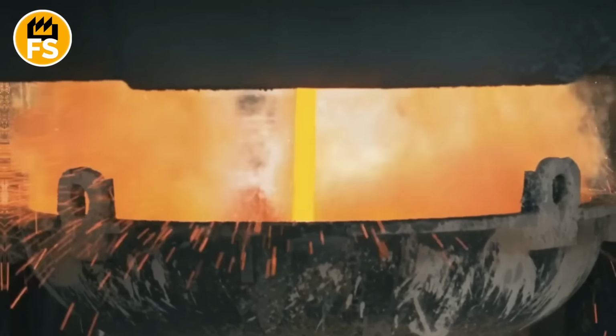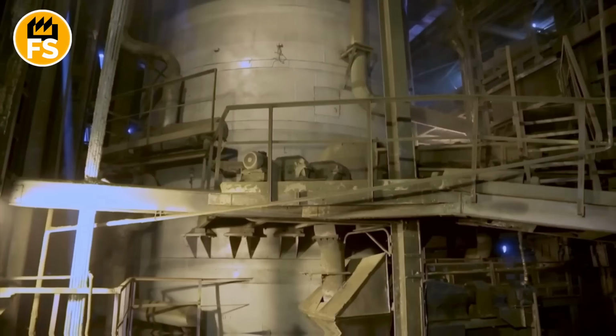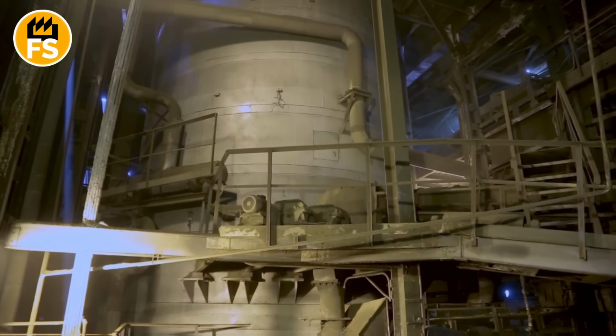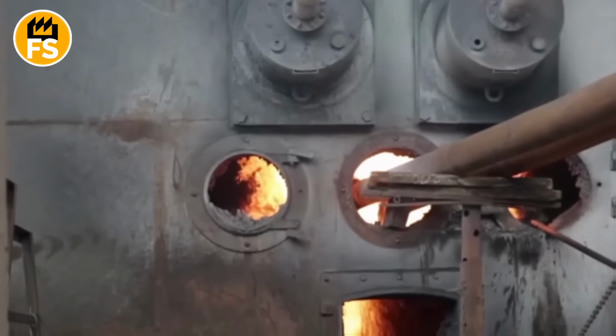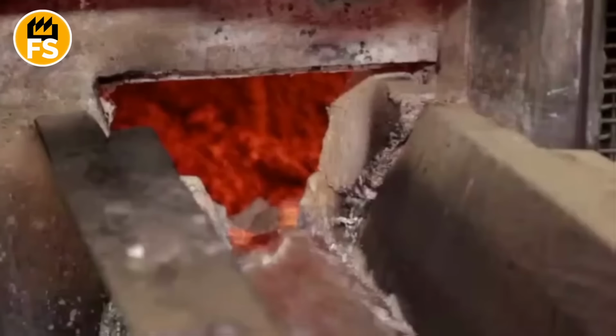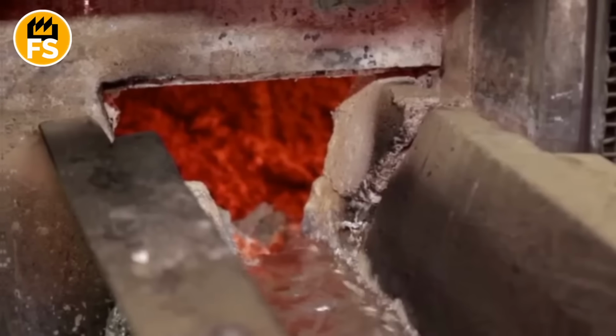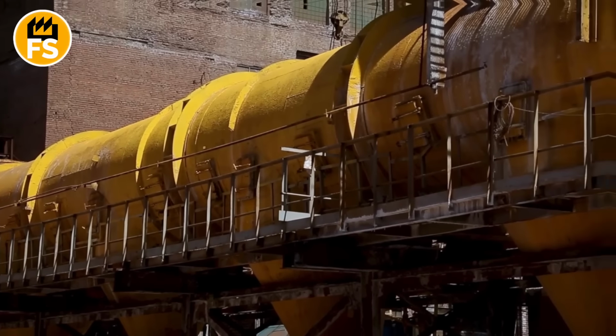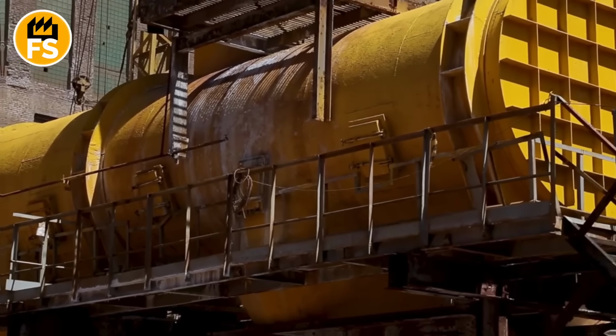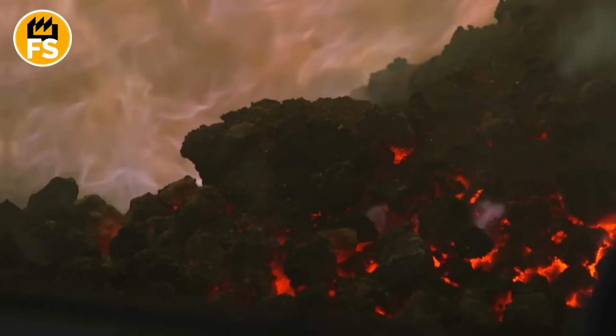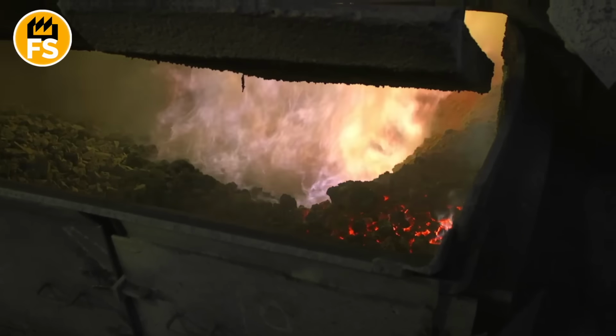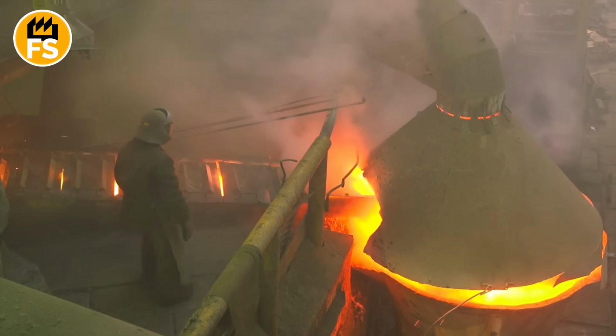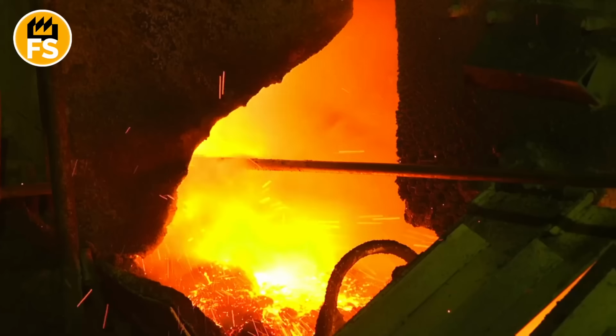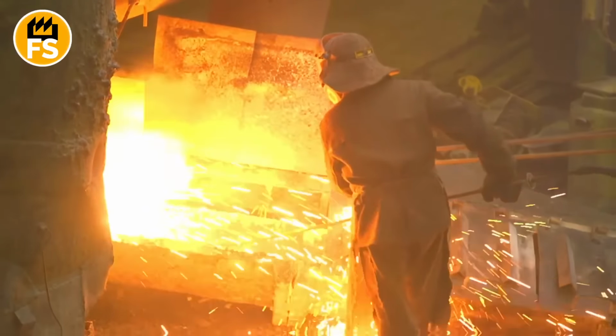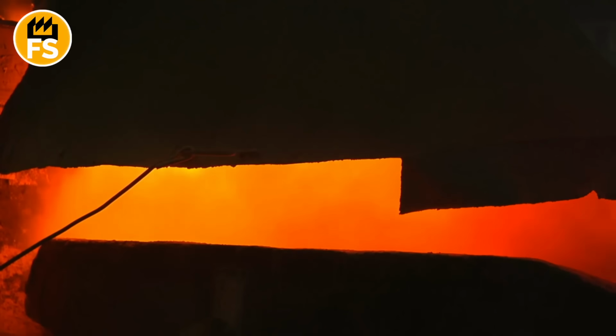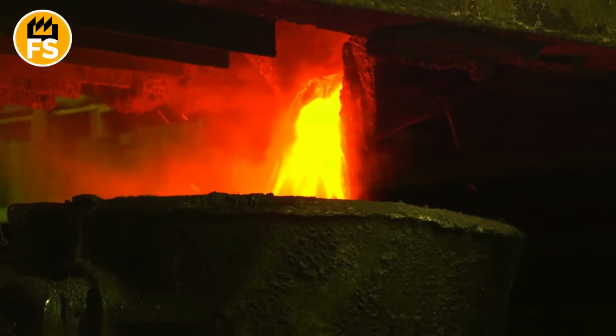The most common method is pyrometallurgy, which involves several stages. First, the concentrate is roasted in special furnaces at high temperatures. This is a calcination process that removes sulfur from galena, converting it into lead oxide. The sulfur that's released as sulfur dioxide gas is carefully captured and converted into sulfuric acid to prevent air pollution. Then the lead oxide is loaded into large blast furnaces, where it's mixed with coke and fluxes. In these furnaces, at temperatures over 2,000 degrees Fahrenheit, a reduction process takes place. The carbon from the coke pulls oxygen away from the lead oxide, releasing liquid metallic lead.